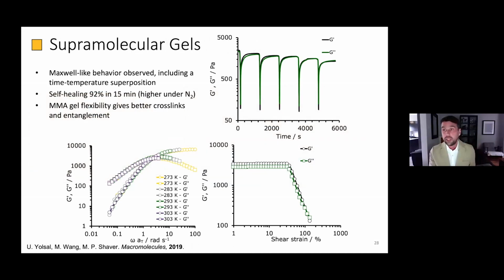For those of you who like rheology, I'll just skim through this quickly, but I'm not going to go into it in terms of detail. Important takeaways are in the top left here. You can see that we don't have full recovery. And this is because we do have a Lewis acidic species that is quite sensitive. It's a very reactive system. And so because I have that in there, when I break those crosslinks and then I try to reform them, when they're broken, there's a brief period of time where those are sensitive to water or oxygen.